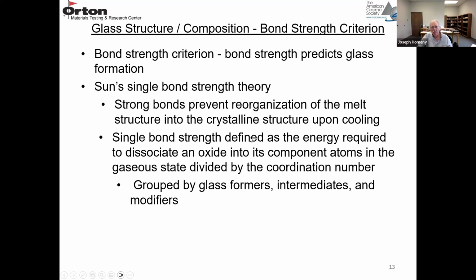And a single bond strength is defined as the energy required to dissociate an oxide into its component atoms in the gaseous state, and that's divided by the coordination number. So he groups them as glass formers, which would be something like SiO2, that forms a glass by itself. Glass intermediates, which do not form a glass by themselves, but will form a glass if there's a glass former present. So an intermediate might be Al2O3. And then glass modifiers do not form glasses, they just modify the glass structure. So glass formers, glass intermediates, and glass modifiers based on their bond strength.